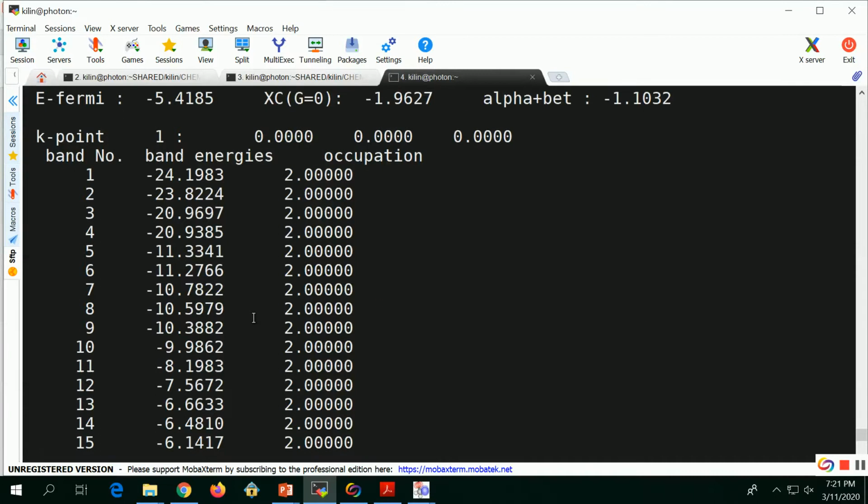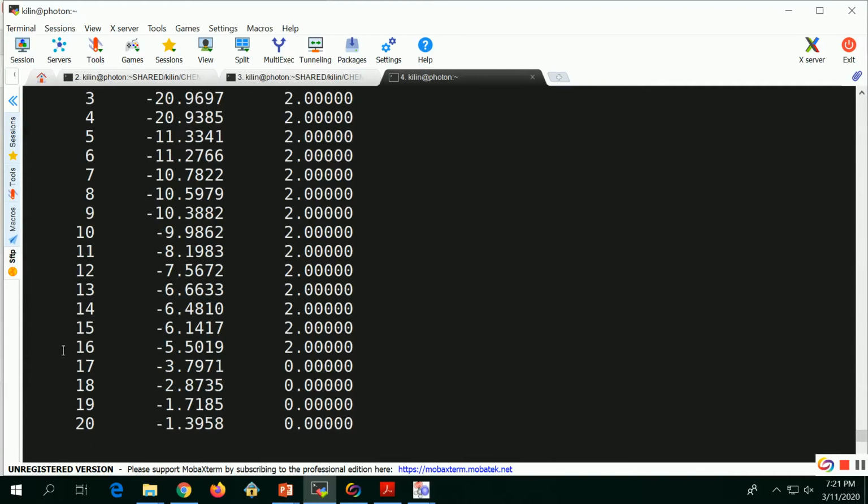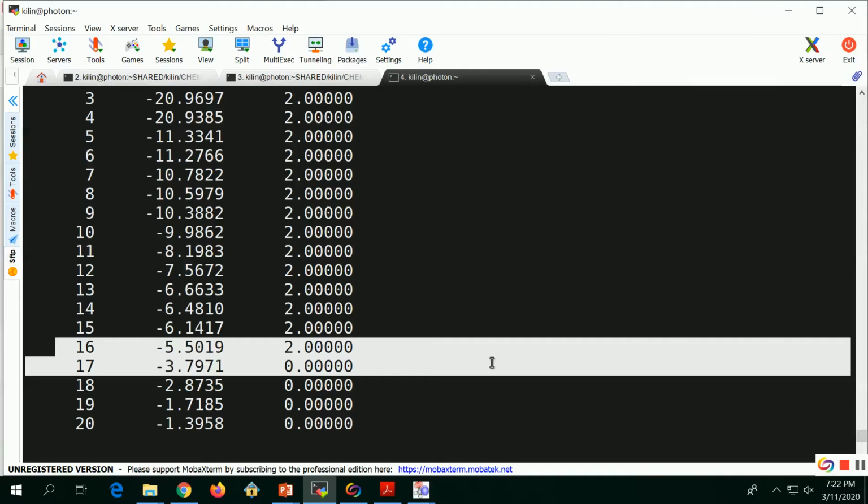One needs a spot in the OUTCAR file that follows the word Fermi energy. There is a list of orbitals, a list of their energies, and a list of the number of electrons occupying each orbital. For this model, the HOMO-LUMO gap is substantially smaller compared to Hartree-Fock that we were doing in Gaussian. It's about 2 electron volts. We didn't optimize. Maybe there is an accumulation of other errors, but please try to look into the OUTCAR file and find this record. I will compose a homework for doing calculations for a few other models and finding these values there: energy of HOMO, energy of LUMO.